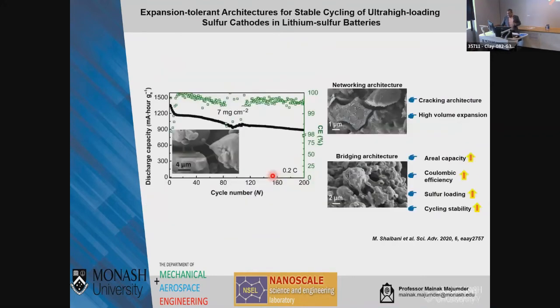And this is the work of Majumder, published a couple of years ago on lithium-sulfur batteries, where we discovered a new way to make cathodes which are expansion tolerant. We changed the microstructure of a traditional cathode to have these bridging bonds. So strong mechanical bonds made of polymers, and what it does is it allows the cathode to expand and contract with a very high sulfur loading. Usually you would have a networking architecture. We engineered the binder to make what is called a bridging architecture.